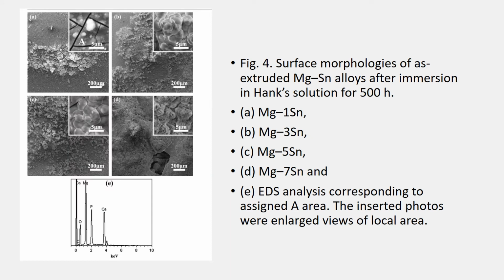This is Figure 4. It illustrates surface morphologies of as-extruded magnesium tin alloys after immersion in Hank's solution for 500 hours. A shows Mg-1Sn, B shows Mg-3Sn, C shows Mg-5Sn, D shows Mg-7Sn, and E shows EDS analysis corresponding to the area in A. The inserted photos are a larger view of the local area.